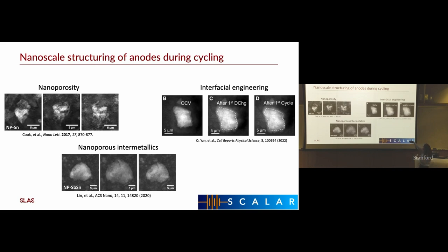But with nanoporous intermetallics, we were able to preserve both the nanoporosity at the local structure, but also the large micron-sized particle size. And then the interfacial engineering allowed us to really do that as well without the nanoporosity. So there's many options when you want to be designing these novel anode materials.